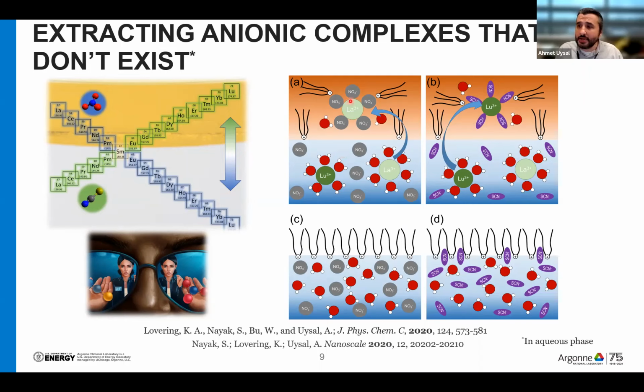And one is your extraction trends depend very strongly on the anion that you choose. So here's the lanthanide series. What I'm showing here is if I choose nitrate as a background salt in this extraction process with quaternary amines, I can extract light lanthanides very nicely, but the trend goes down and I cannot extract heavy lanthanides. If I switch my anion to thiocyanate, this trend completely reverses. Now I cannot extract light lanthanides, but I can extract heavy lanthanides.